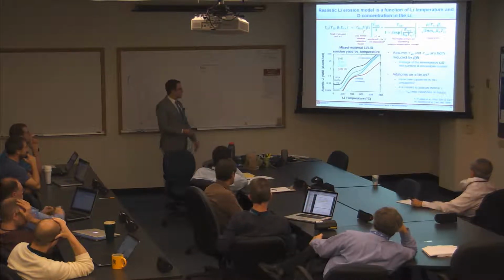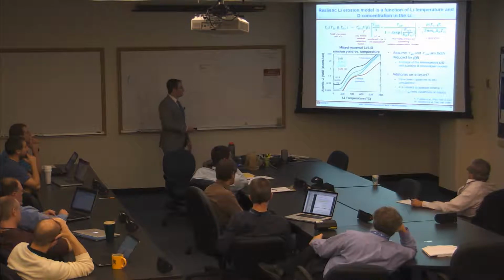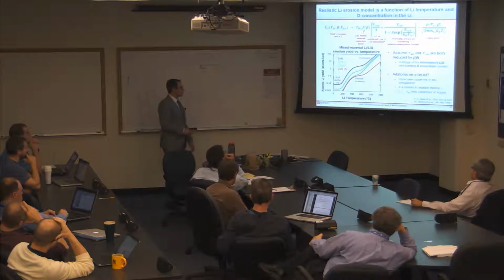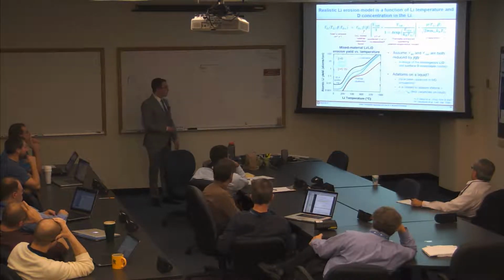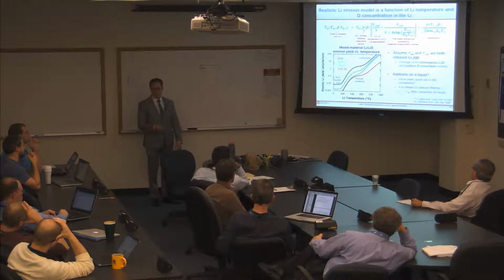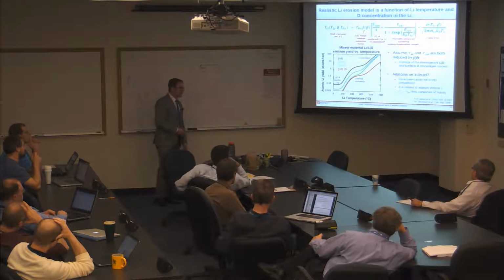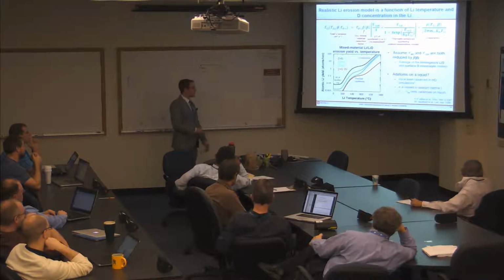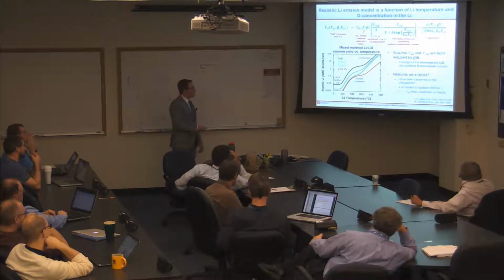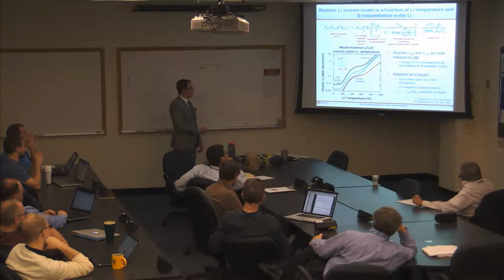So what does this look like if you plot it as a function of the lithium temperature? Well, at very low temperatures, it's just binary collision approximation sputtering, so it's constant. Then it starts to increase very quickly because the thermal sputtering term dominates. And then it starts to plateau between about 400 and 600 C. Physically, this is assumed to correspond to the evaporation rate of these add atoms becoming limited by their rate of production on the surface. And then it starts to take off again around 600 C or so due to evaporation.